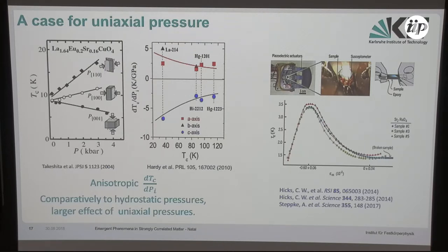But it was quite clear that the response of the critical temperature of that material to hydrostatic pressure is a compromise between the antagonistic effects of uniaxial pressures that just have opposite effects. So along the c-axis it decreases Tc and in the plane it increases Tc. And I thought it would be much more interesting to look at what happens when you apply uniaxial pressure in a controlled way.